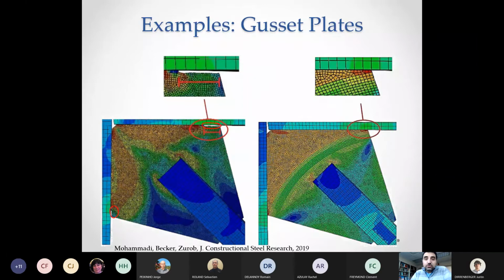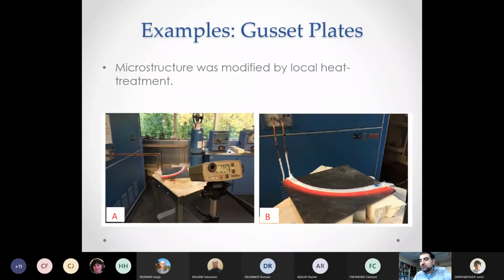So the idea that they wanted to try was to create a material where there is this band in the middle. You can see an arc going through the material here, where through this arc, the material is a little softer, maybe 20% softer than the rest of the steel. And then according to their simulations, the material will not fail in these areas. So initially we wanted to decarburize the material in this region. And then when they showed me how big the plate was, I realized it wasn't going to fit inside my furnace. So we chose a different approach to do this.